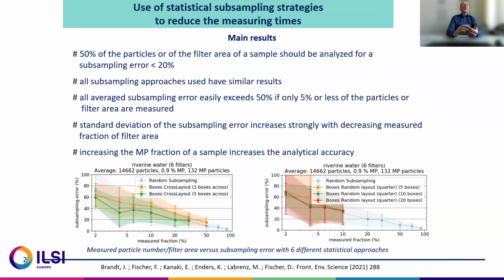A very important point is subsampling. A lot of people use it because we have so many particles and the measurement time can be between 2 hours and 5 days. We tested different algorithms, and the main result is that 50% of the particles or of the filter area, both is possible, should be analyzed for an error below 20%.